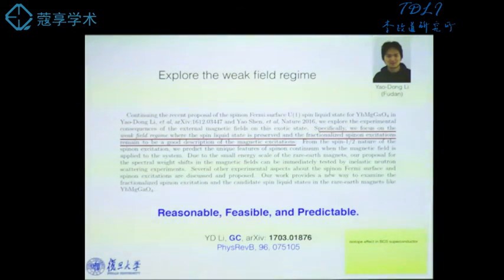So we use a weak magnetic field. The field cannot be large. If the field is large, the spin gets fully polarized. So you destroy the spin liquid state. Imagine the spin liquid was there originally. Now you apply a strong field, the spin gets all polarized. So the state is gone completely. So to keep the state there, we use the weak field. The weak field just does something little to the system, because the spin liquid is robust against small, weak perturbations.